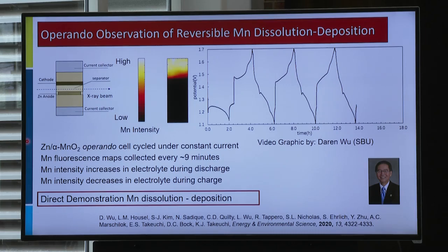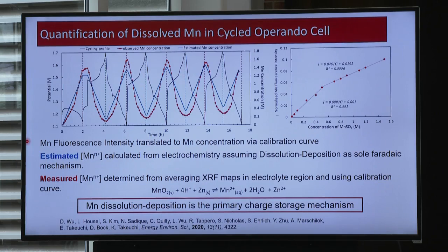So what we wanted to do was quantify this, so not just a qualitative observation, but a quantitative observation of the dissolution and deposition. So we established a calibration curve using multiple concentrations of dissolved manganese in the electrolyte, and then tracked and quantified, based on the micro X-ray fluorescence behavior, the amount of dissolved manganese in the electrolyte and compared it to the electrochemistry. And what we observed was that if we quantify it, the dissolution of manganese and the manganese concentration in the electrolyte is really the dominant electrochemical mechanism that's taking place.